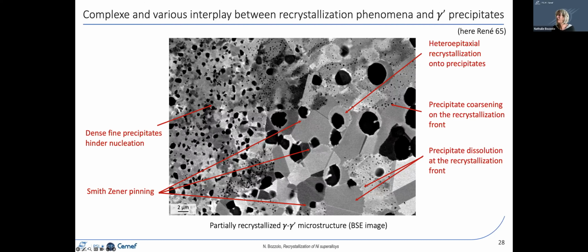But we can also notice that we have fine precipitates in the work-hardened grains, but none inside the recrystallized grains. So there is a mechanism by which the small precipitates which are present in the deformed matrix disappear or are dissolved or transformed into something else while the recrystallization front goes through them. Actually, we nowadays believe that it's a kind of accelerated Ostwald ripening mechanism, which makes the small precipitates dissolve and makes a few ones grow and form these additional types of precipitates.